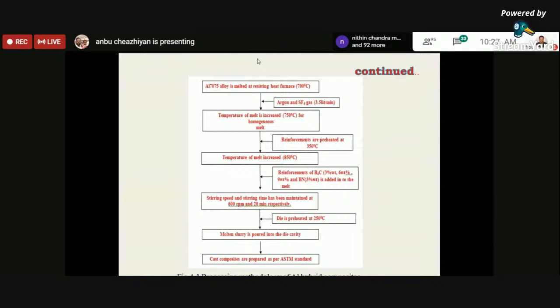In order to have a homogeneous melt, the temperature of the melt is increased to 750 degrees centigrade. After that, the reinforcement particles are preheated to 350 degrees centigrade to remove the moisture present in the particles, so that we can also avoid oxidation. We have also increased the temperature of the melt to 850 degrees, the maximum limit, since the melting temperature of boron carbide is 1100 degrees centigrade, to obtain a fine grain, a fine interdendritic pattern.